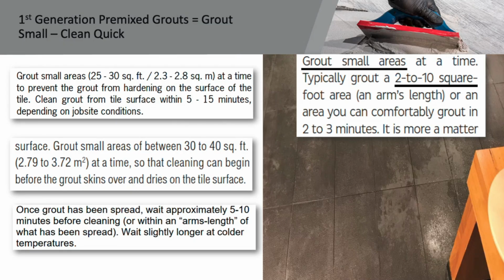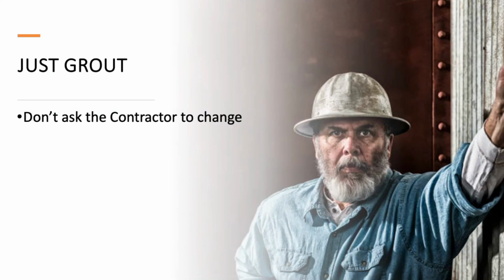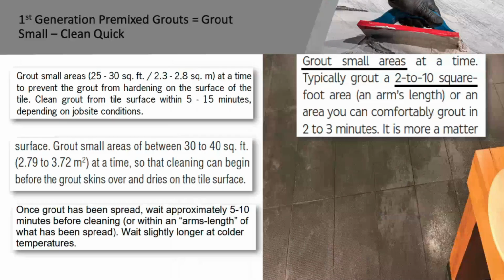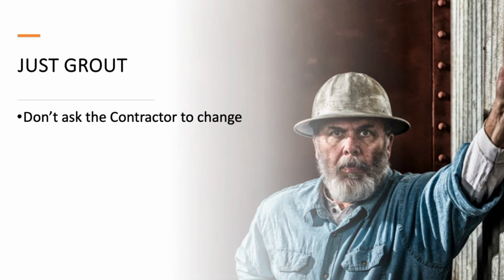So what we found out from the contractors is that they like the product, but the cleaning was so difficult to be able to get it off there quick enough. And then they ended up starting to do it like an epoxy job. So the contractors would do it with a helper, and one person would spread the grout, one person would clean the grout. So that worked, but labor costs went up. So now all of a sudden you're getting back up into that epoxy application. And I actually had some contractors that would rather have used the epoxy than the premix, which wasn't working for us. So we wanted a grout where we didn't have to ask the contractor to change.